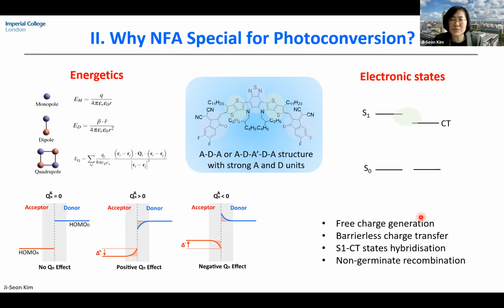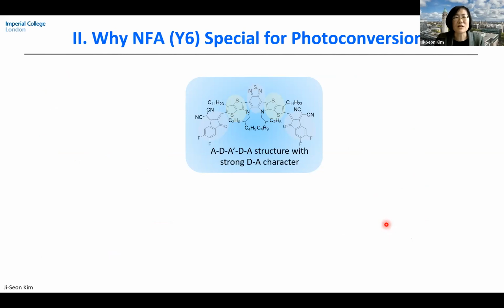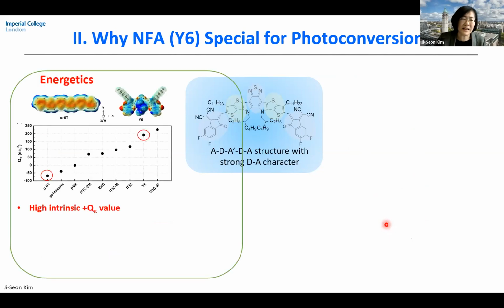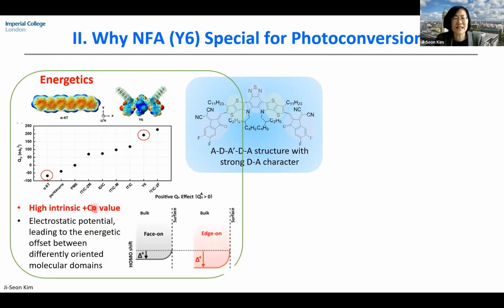So how this charge transfer acts in order to generate charge carriers or recombinations is another thing we need to consider. So for the Y6 case, when we first looked at the energetics and calculated the Q pi value, we found that Y6 shows a really high quadrupole moment compared to, for example, alpha-6T. It is because it has a non-uniform charge distribution because of donor acceptor character along the conjugated backbone. So having this high intrinsic positive quadrupole moment, as I explained, will influence the bulk energetics as well as interfacial surface energetics.